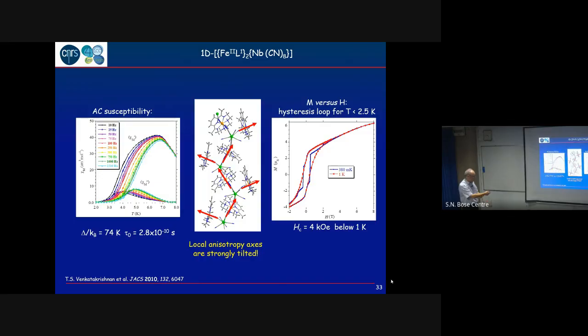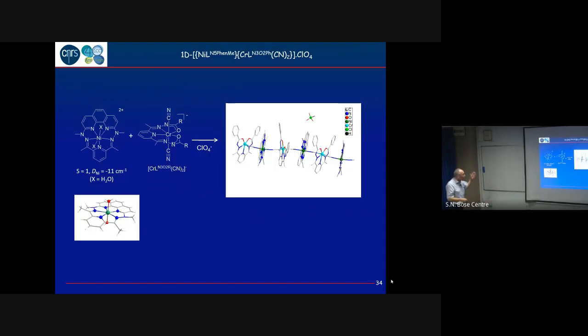In this case, you see that the zigzag arrangement here is because the cyanides are not just opposite. We don't have 180 degrees. You end up with something that is this kind of zigzag arrangement. So when it's perfectly linear, like here, you end up with a chain that looks like this one.